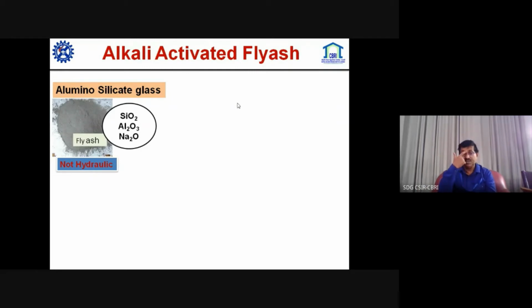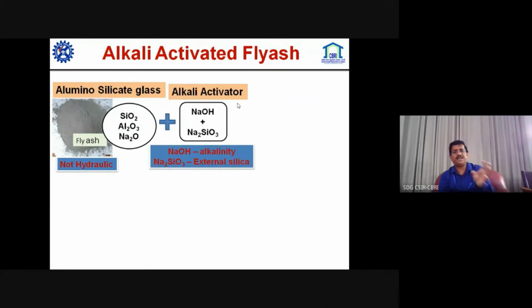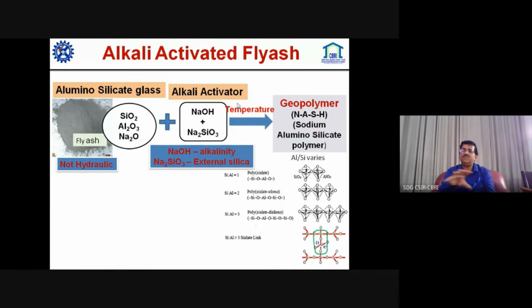Basically, fly ash has silica content of about 35 to 60%, alumina content, sodium oxides, and all those things. So we are activating with sodium hydroxide and sodium silicate, usually in a very high alkaline medium. And if there is a lesser silica content, we give some 60-degree to 80-degree temperature, and we are converting it into geopolymer, which is nothing but a sodium aluminosilicate polymer. But if you have to do it at ambient or normal temperature, you have to add something so that some energy, some temperature, is enhanced.